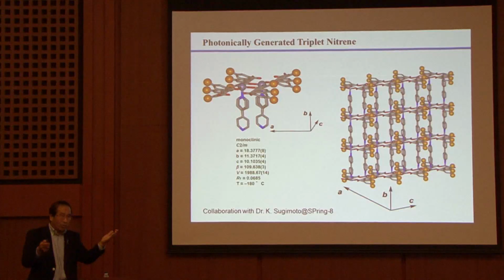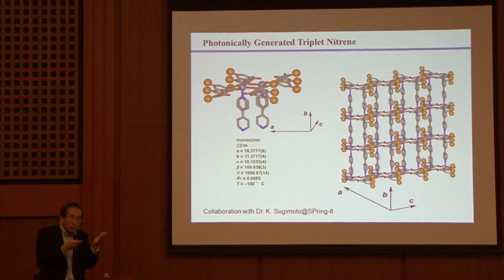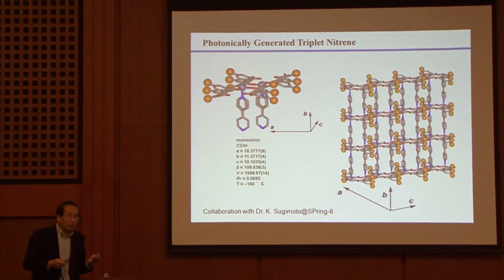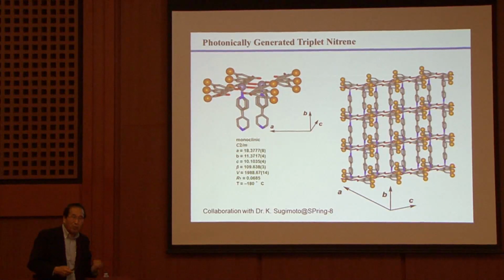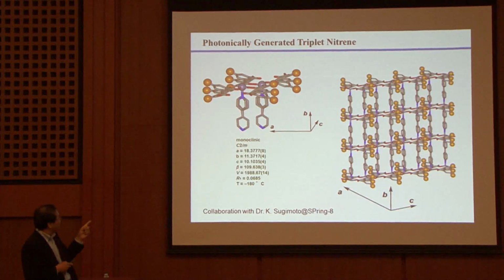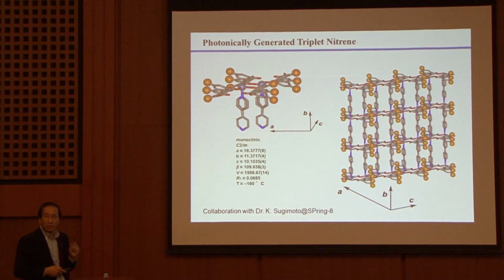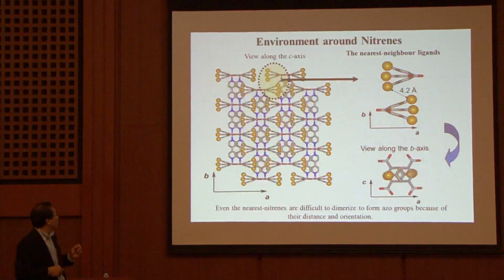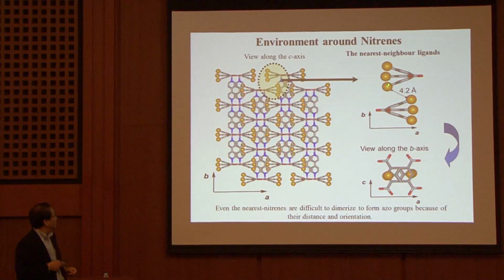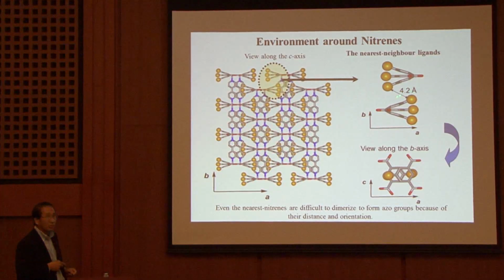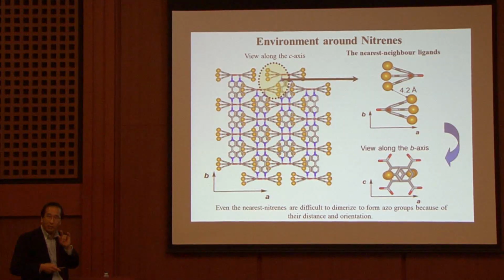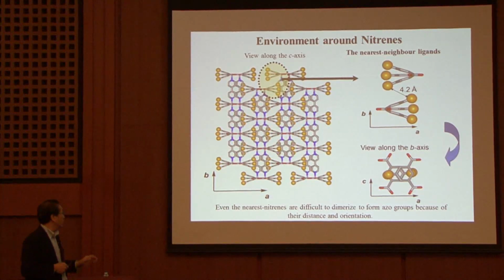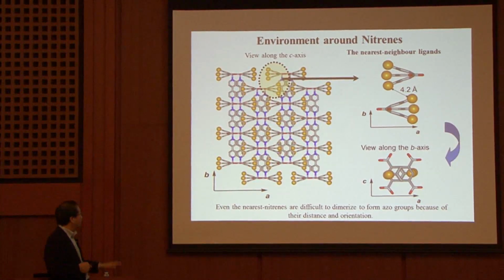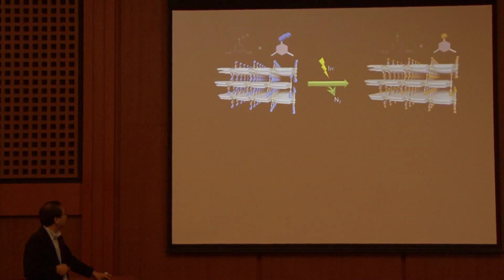As you know, Katsuki Sensei knows, and organic chemists know, this species is very reactive and impossible to maintain. But here it is stably maintained at this site, because the closest distance is 4.2 angstrom. There is no chance of a coupling reaction in this case. So fortunately, we obtain this kind of very reactive species.